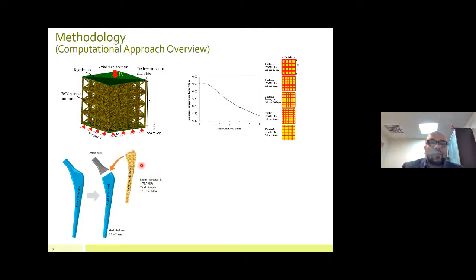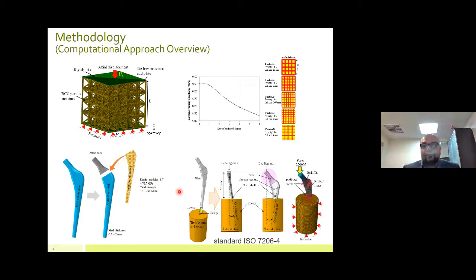So this whole volume of the porous structure reduced the mass of the overall implant compared to the bulk titanium, and also managed to reduce the stiffness of the bulk titanium close to that of the bone. And then by using the ISO standard, we managed to conduct our studies again through the computational approach.